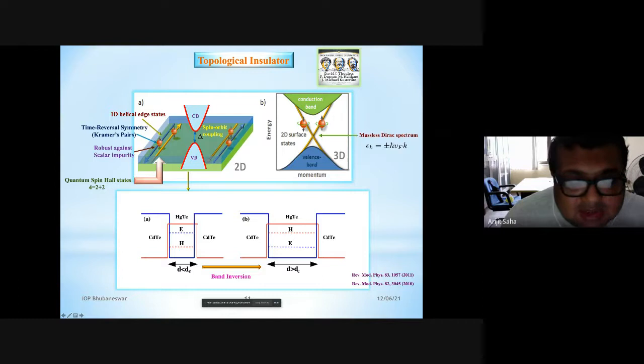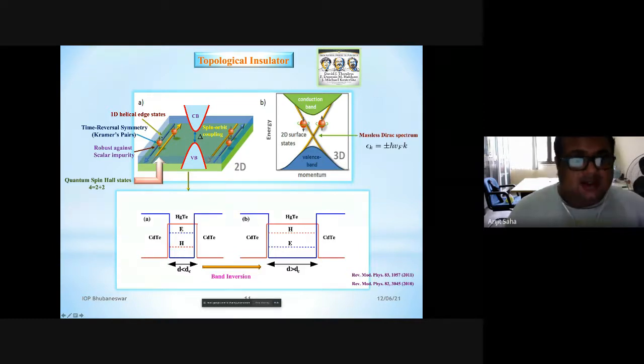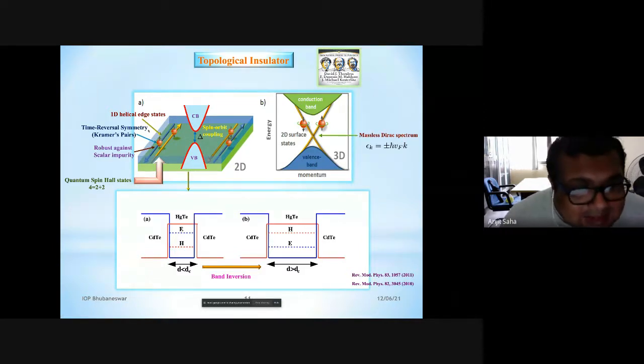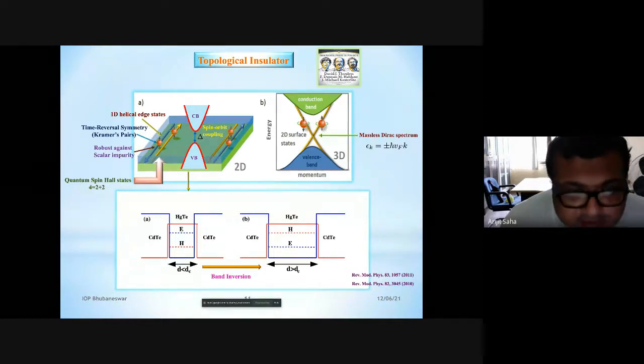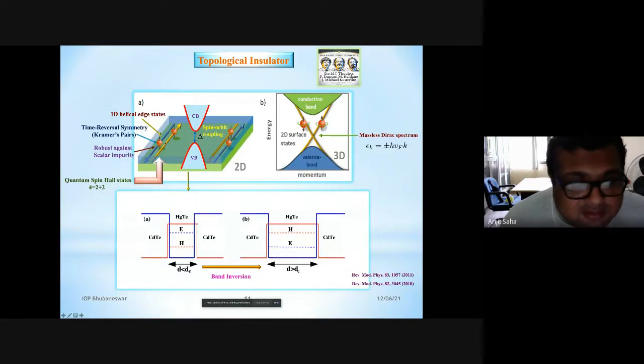The spin and momentum are coupled here. And the direction and the spin just reverse if you go to the other boundary. So it will be like this, and immediately these two edge modes are actually a Kramers pair due to the time reversal symmetry here. And also they are not called chiral, now they are called helical. So it's like sigma dot p. So it's a helical edge mode, and they are time reversal symmetric partners of the time reversal symmetry present in the system.